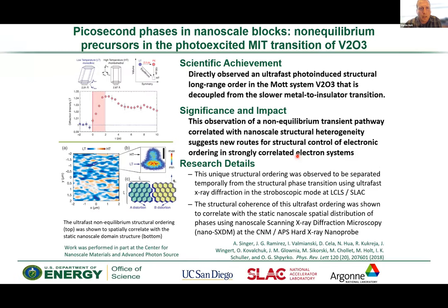So this has also been done in terms of overlapping this nanoscale mapping with LCLS style ultrafast diffraction. If you know the real space ordering of this kind of uninteresting mosaic disorder, you can understand the scattering stability that you're seeing on these ultrafast timescales within the context of this real space pattern. So this work has already been done and I feel like this is going to be getting a lot better under the upgrade. And so that's something to keep track of.